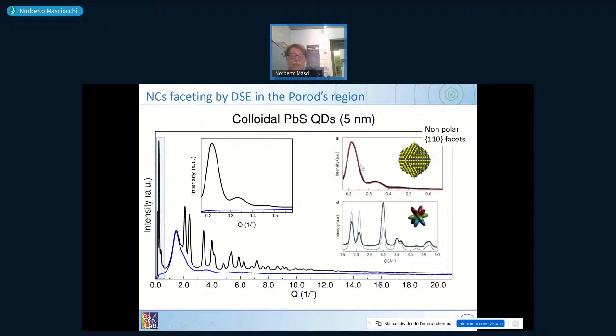If we take our material and deposit it on a silicon surface and do the normal Bragg or normal powder diffraction experiment, instead of having the ideal intensity, which is measured here in the blue line, which matches more or less what you see here, you have extreme intensity for this peak, a much lower intensity for the second one, and altogether you have distortion of intensity. This means that your powders are not real powders, but are oriented materials, which on the surface of the silicon expose specific phases.